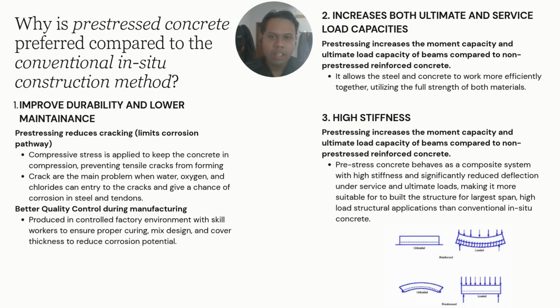Second is increased ultimate and service load capacities. Prestressing can increase the moment capacity and ultimate load capacity of beams compared to non-prestressed reinforced concrete. It allows the steel and concrete to work more efficiently together, utilizing the full strength of both materials. Higher stiffness: prestressed concrete behaves as a composite system with higher stiffness and significantly reduces the deflection under service and ultimate loads, making it more suitable for structures with longer spans and higher loads than conventional in situ concrete. A prestressed concrete beam can go for longer spans of 25 to 45 meters, while a reinforced concrete beam basically goes from 10 up to 15 meters.